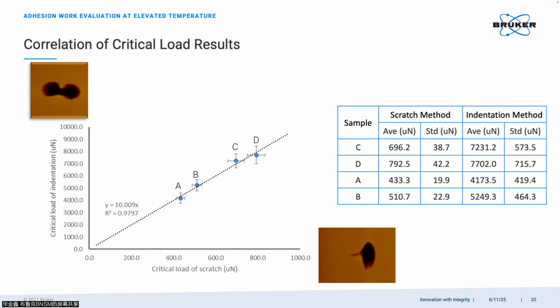And you can see that for these four interfaces, no matter the indentation method or scratch method, if your interface is strong, the critical load collected from indentation will be the highest. Similar behavior will happen in the scratch test. And just like I said, for a lot of cases, you will find these two data sets of critical load are proportional to each other. That means, for example, the proportion here for this case is around 10 times.